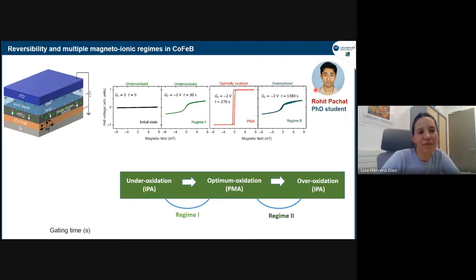So this is once again a similar system, cobalt-iron boron, but this time on tantalum. Once again, hafnium oxide, ionic liquid, and the top electrode. Here we start, like in the cobalt case, with a state that doesn't have PMA. If we apply a negative voltage, we pump oxygen towards the cobalt-iron boron, and we see that the system starts going to PMA. Then at some point, for a given gate voltage and gating time, we have a nice PMA state. But if we keep oxidizing, then the PMA will decrease.